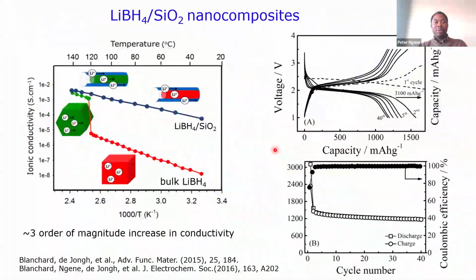Okay, so this is the first proof of point. The same lithium borohydride which I worked on before for hydrogen storage. Now, if you put it in silica, what you see here is that this is the bulk-like behavior. We have already seen this. The phase transition happens here, associated with high conductivity. But if you put them inside these very small pores, already at room temperature the ionic conductivity has about 3 orders of magnitude increase.